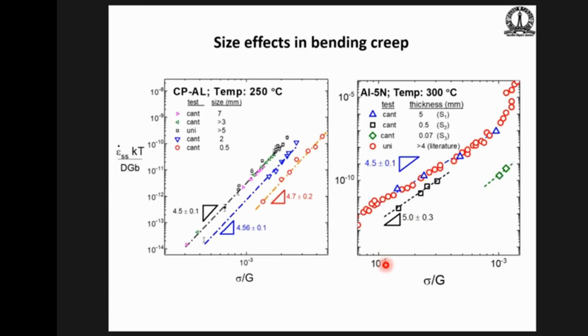And we argued that, so here's another example, this is commercial purity aluminum. This is 5 nines aluminum, 250, 300 degrees. Again, this top set of data are for what's called bulk, anything which is 3 and above. And here, we're progressively reducing the thickness of the beam. And you'll see very dramatic differences. I mean, in this case, it's probably 2 or 3 orders of magnitude strengthening that you get from small beams.